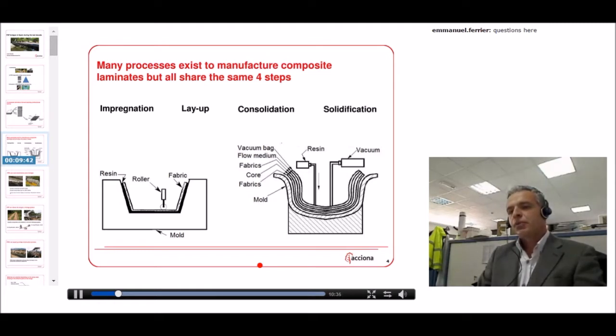Here I have put two examples of two manufacturing processes. On the left, you have a wet layup process. It's very simple, in which you put a layer of resin on a mold, generally a steel mold, then you put dry fabric on top of the resin, and then with the roller you push the dry fabric against the epoxy resin layer. In this way you can get the dry fabric wet and at the same time consolidate the laminate, and then you can supply heat to the laminate to cure the resin. In this way the resin gets solid.